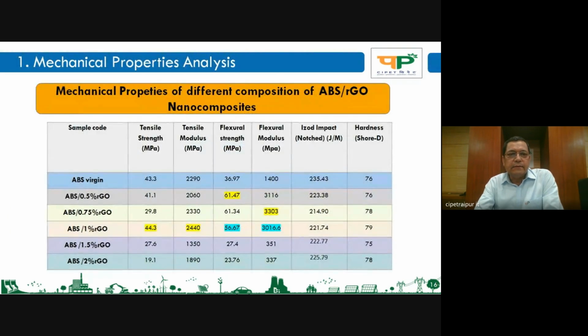All these results have been taken and analyzed. If we go through one by one, we have ABS virgin, then ABS with 0.5% RGO, 0.75% RGO, 1% RGO, 1.5% RGO, and 2%. These different combinations we have taken, and whatever results have come, we have tabulated. And if we see this, with 1% RGO we are getting the optimum result.